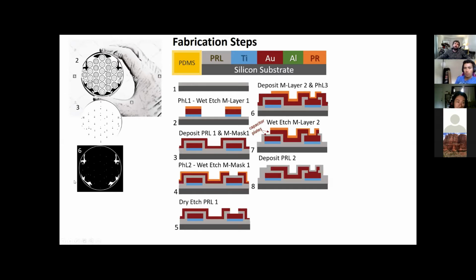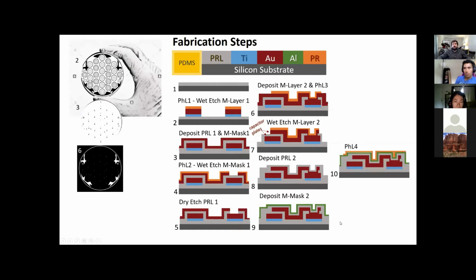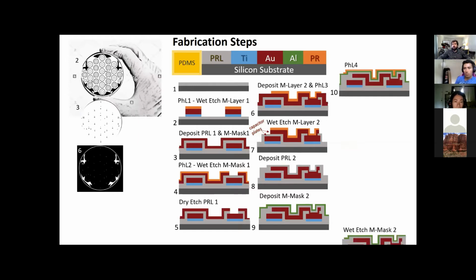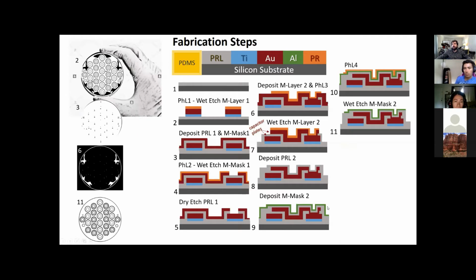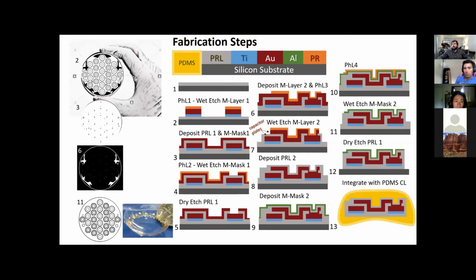And this is how it looks from the top view. And this is the side view, by the way. Then I eventually covered it with Parylene C for the last step of packaging, and then I released the device by creating these aluminum metal masks so that I can dry etch the entire residual Parylene C. Then when I did that, I released the devices off the wafer, and using cast molding, I created these contact lenses.